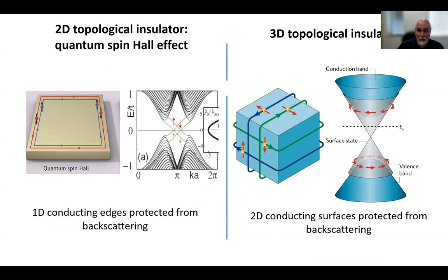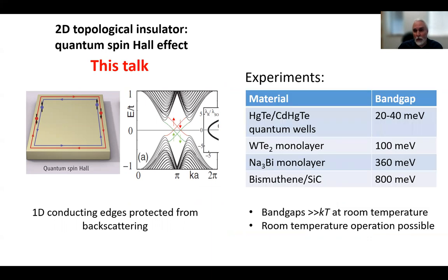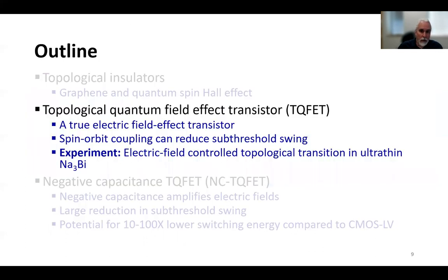We now know that there are 2D and 3D topological insulators. The 3D topological insulators are also insulating in the bulk. And they have conducting surfaces where spin and momentum are coupled. In this talk, I'm going to focus on the two-dimensional topological insulator. Experimentally, there are quite a few known materials now. Mercury telluride quantum wells are the first example. Tungsten ditelluride monolayers, sodium-3-bismuth that I'll talk a little bit about, and bismuthene are some good examples. These materials can have very large topological band gaps, and so, in principle, they can function just fine for devices working at room temperature.